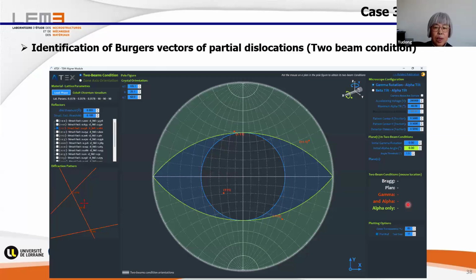And now it's the software. But now Benoit added a lot of things. The page changes. It's not this configuration, but you can find all the information here. So first, we have to introduce the phase, because we need the phase parameters to make a crystallographic calculation. And so we should give the correct phase. And after that, we have to select which work we would like to do. So it's a 2-beam condition. And now we have to enter the orientation with all the angles here that we determined.